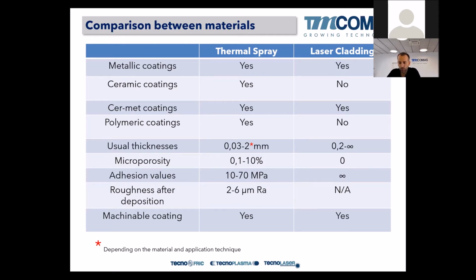Microporosity in thermal spray, we can play with the parameters to have different levels of microporosity, between 0.1 and 10%, I would say. While in laser cladding it is 0. If the welding is correctly done, the porosity should be 0. Adhesion values are 10 to 70 MPa in thermal spray, and in laser cladding it is virtually infinite because there's a welding. So the adhesion is the mechanical properties of the clad, not infinite, but limited to the feedstock mechanical properties.